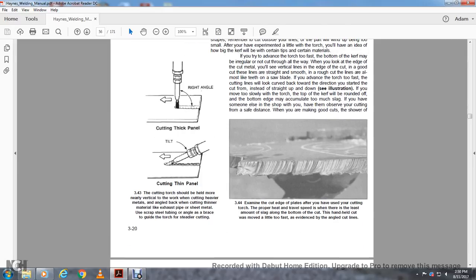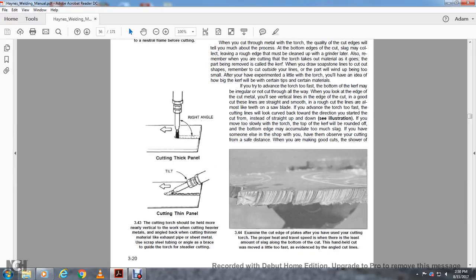344. Examine the cut edge of the plate after you have used the cutting torch. With the proper heat and travel speed, there is the least amount of slag around the bottom of the cut. This handheld cut was made a little too fast, as evidenced by the angled cut lines. If you move too slowly, the top of the kerf will be rounded off, and the bottom edge will accumulate too much slag.